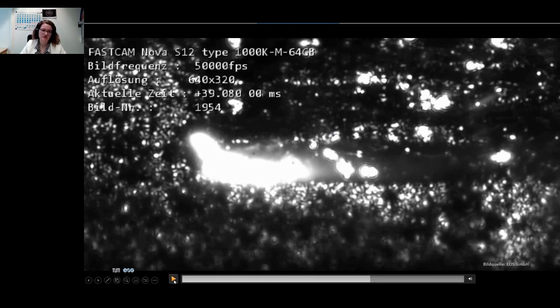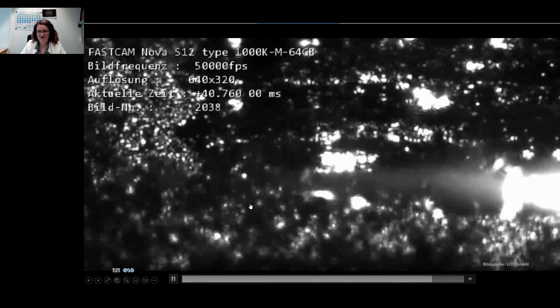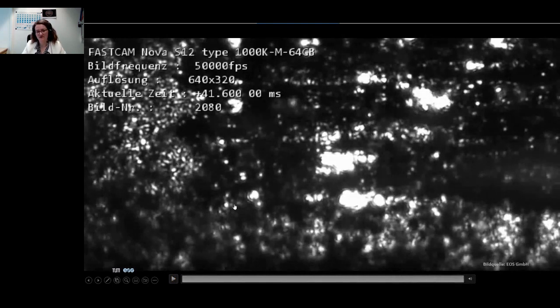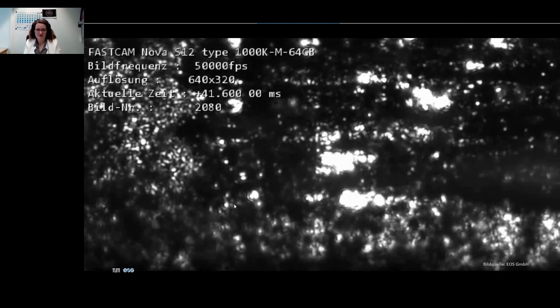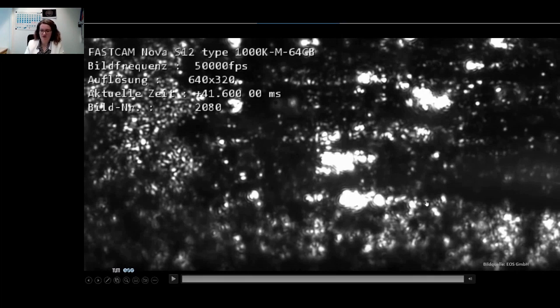And due to this highly dynamic process, the spatter formation, and overheating effects, there is quite a high probability that you have defects in your component. And actually, our aim is, first of all, to increase the production speed, but also to increase the stability of the process.